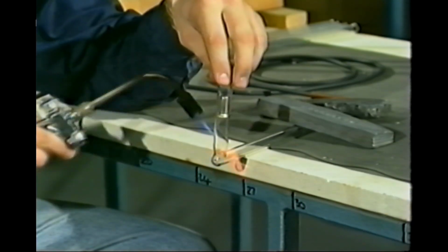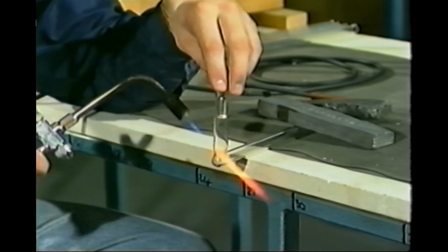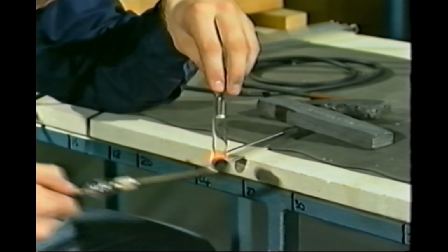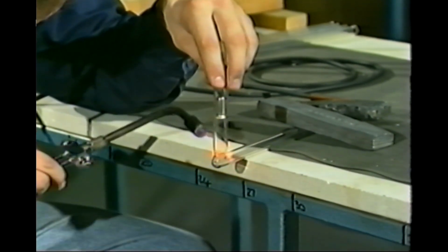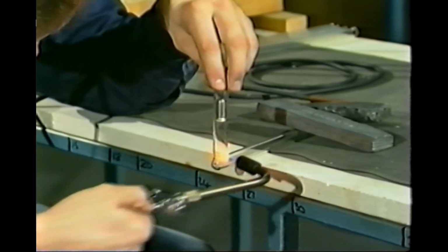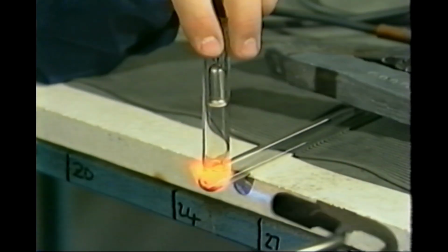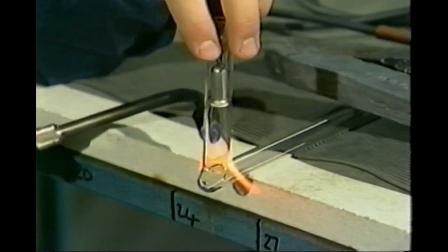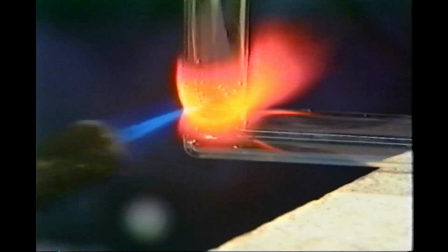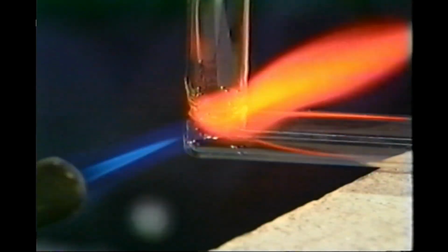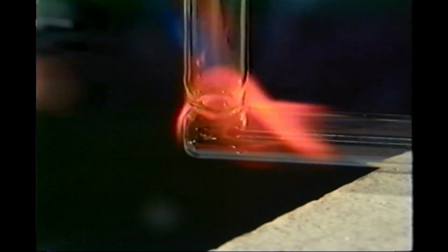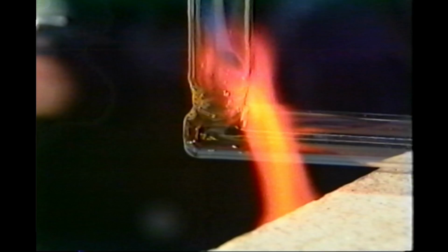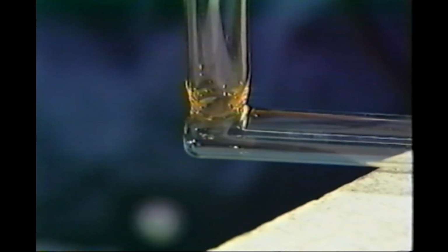Quickly set up the same small, sharp flame used previously. Keeping the flame at right angles to the electrode, melt across the joint line with complete rotations. Hold the electrode steady, not allowing any upward or downward movement during this melt. When the glass is showing a bright red to orange heat, remove the flame.